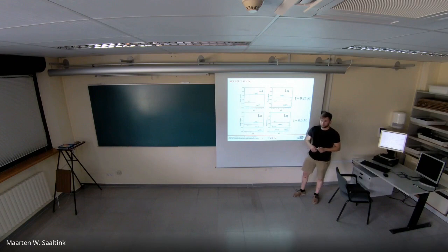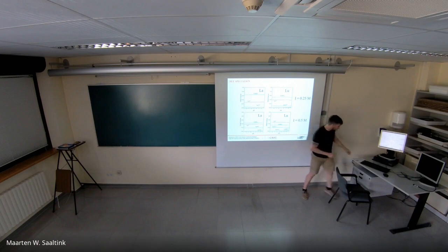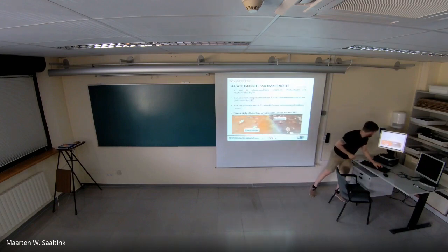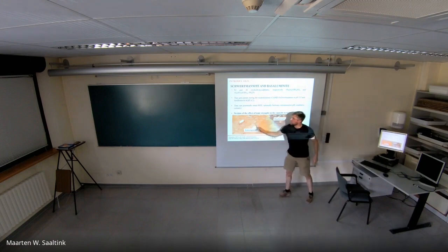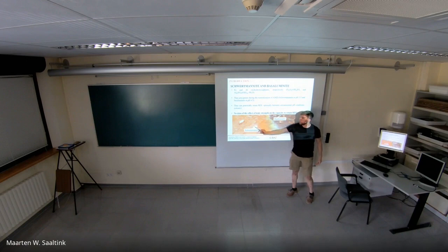But can you say then, for instance, schwertmannite has a high preference for lanthanide? Yes, it has a higher. The problem with schwertmannite is that it is formed at very acid pHs. So in the previous study cases, for example, this one, since this is a pH 3.5, it doesn't absorb because the pH is not the optimal conditions.